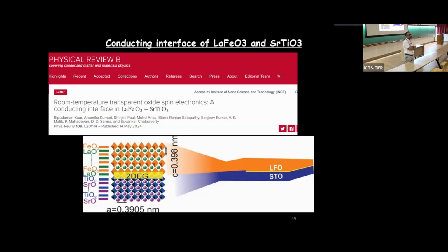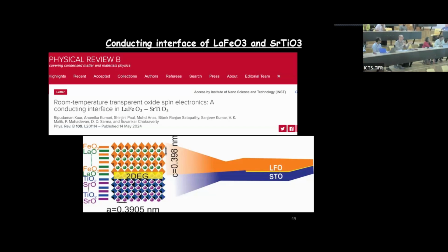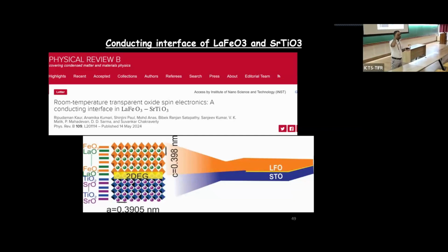Do you see some effect which could not only be attributed to a heating effect from the fluence? I mean, is that an interpretation, or is there something beyond that? Yeah, I understand your point. We also thought about that, but we have no control. When you change the laser fluence, the kinetic energy of this material changes. And so there is a possibility of inverse sputtering from the target substrate as well. And that can also heat up the target, but these we don't have any control over. I understand your point, yes, definitely.